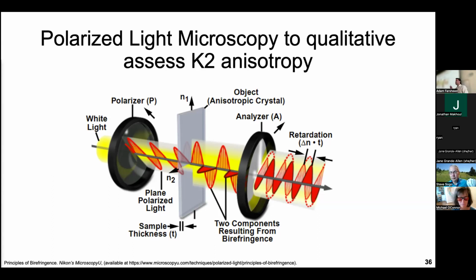But if you're able to put a material that's anisotropic in between those cross polarizers, it's going to split that wave into two different planes. And those two different planes are going to be able to cross through that second polarizer. And so when we look at these images, the brighter the light that we're able to observe, it's more suggestive that we have anisotropy within our material system.